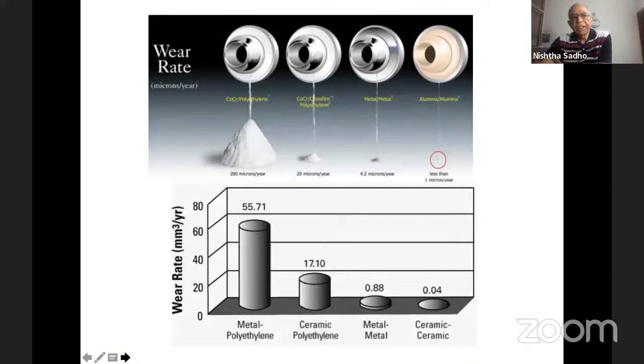So let us see how these different things produce the so-called wear rate. The worst culprit seems to be, per micron unit per year, cobalt chrome on the conventional poly, and the so-called best comes out the ceramic on ceramic. In between, you have the cross-linked poly, and then there is metal on metal also. So putting it in a different way, you have this metal on polyethylene, the worst performer, and ceramic on ceramic is apparently the best performer.